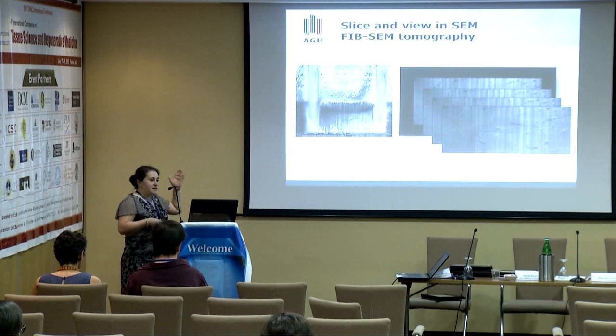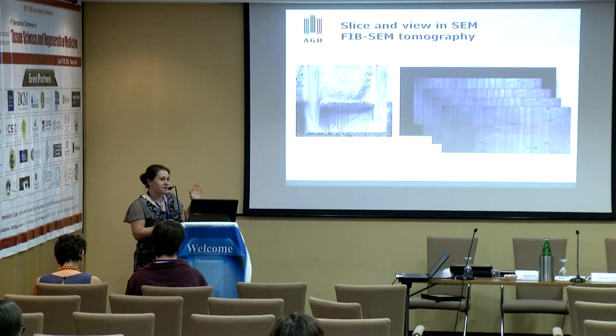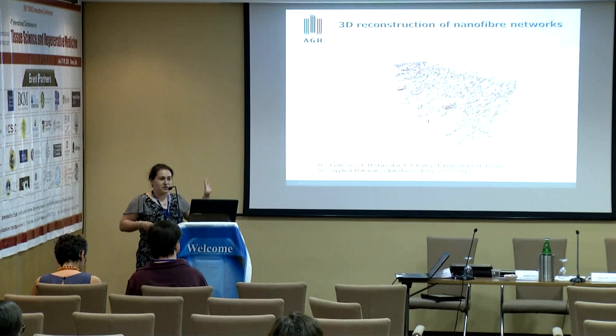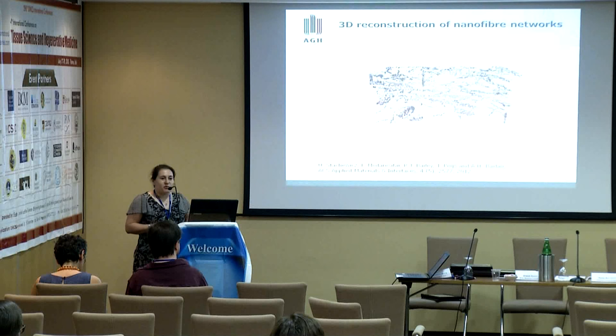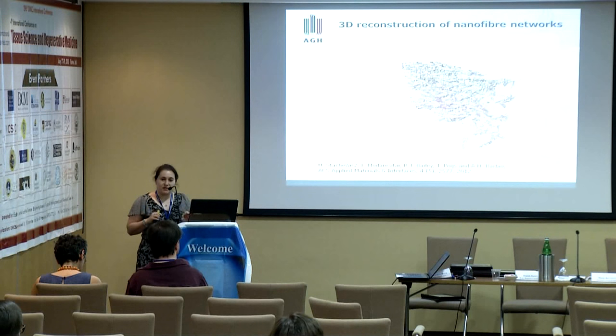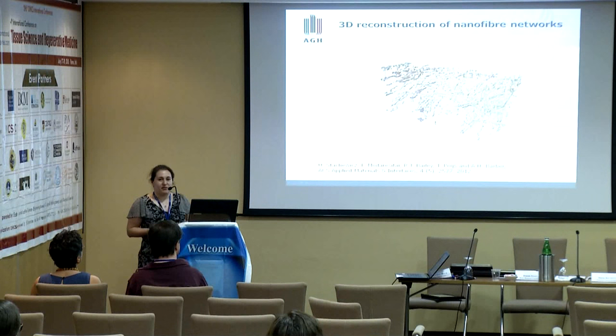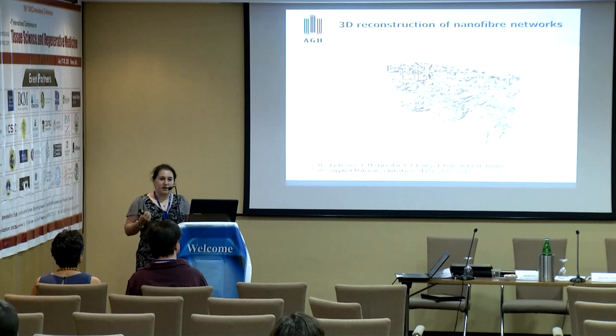We collect slices using a slice-and-view technique and from these slices we do reconstruction of the whole network. This reconstruction of the nanofiber network allows us to calculate the real porosity — the porosity of the scaffolds is around 80 to 90 percent. They are very porous, but the pore size is quite small.